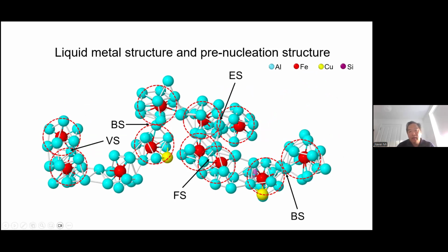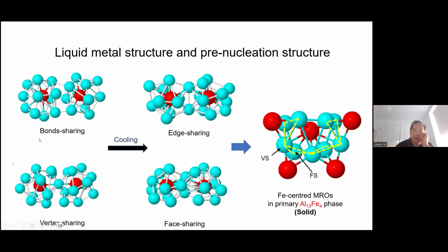Here, you see the complicated interconnection between the clusters with the iron at the center, and that kind of complex cluster connection together, we believe, is the pre-nucleation atomic structure for these particular aluminum-3 iron phases, and how the connections between the atomic structure evolve as the temperature cools down, until reaching almost the crystalline structure of this type of phase, with Al13Fe4, or in another simple word, Al3Fe.